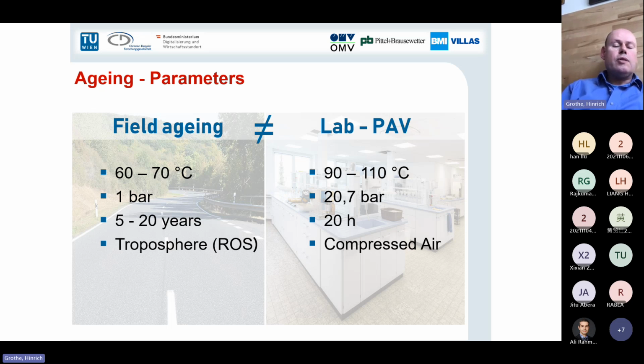Then in the field, of course, you have 1 atmosphere, but in the laboratory, you have 20 atmospheres. In the field, you have 20 years. In the laboratory, of course, you want to do things in a shorter time, so you have only 20 hours. And the main difference, of course, is that in the field, you have the troposphere, including reactive oxygen species, light, while in the laboratory, you handle your sample in the dark and with compressed air.